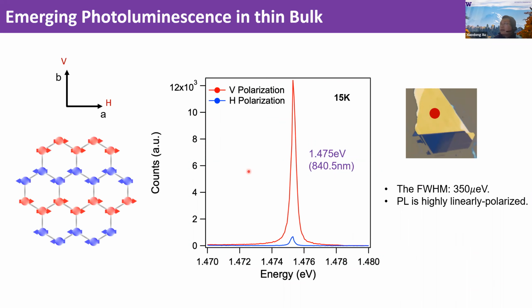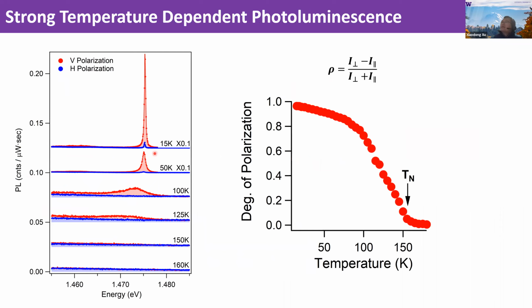So the polarization is strongly polarized orthogonal to the zigzag spin chains. This degree of polarization already indicates that this optical anisotropy is somehow connected to the magnetic order. So we can perform temperature-dependent measurements. On the left side, you see the luminescence as a function of temperature, from 15 Kelvin all the way to 160 Kelvin.